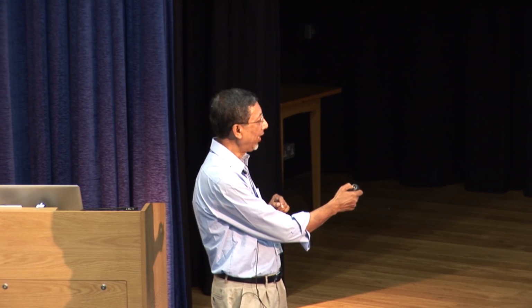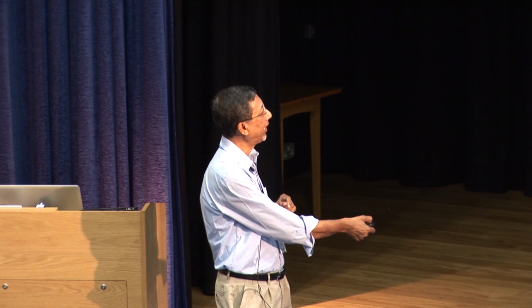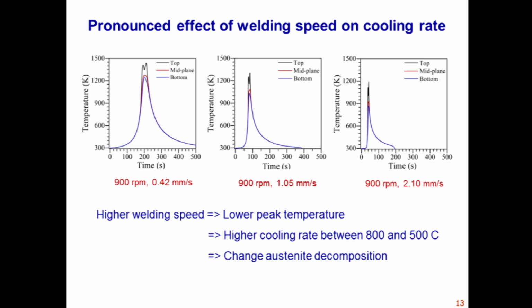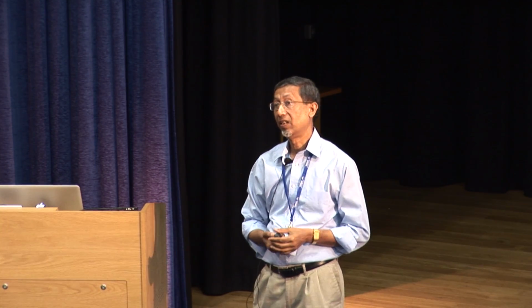Where you can vary the cooling rate is by varying the welding speed, which is like the experience in fusion welding. If you go much faster, you will cool much faster, that is expected. But here, much faster means only about 20, 30 degrees per second in the 800 to 500 degree range. You are not looking at laser welding where you can cool very, very rapidly. It's not that. And it can be as slow as probably 5 degrees centigrade per second. Those are the typical values that we are looking at.